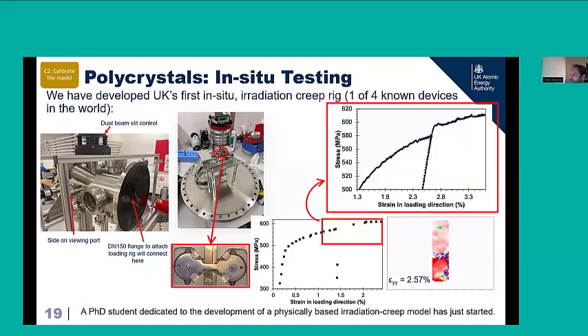And this is a very first data set from that rig showing a test under irradiation where we've loaded the specimen, it's yielded, and then we've unloaded. And as we've unloaded, the material is still exposed to irradiation. And when we reload, we can see that there is an increase in the flow stress, which we attribute to the accumulation of dose during that unload period, and so the irradiation hardening that's happened. And just to mention here that we've got a PhD student who's just started that's dedicated to modeling these effects.